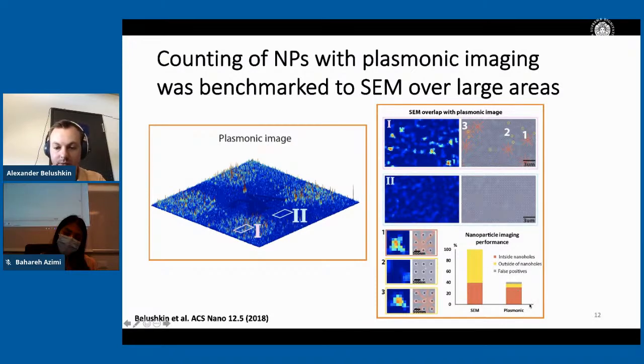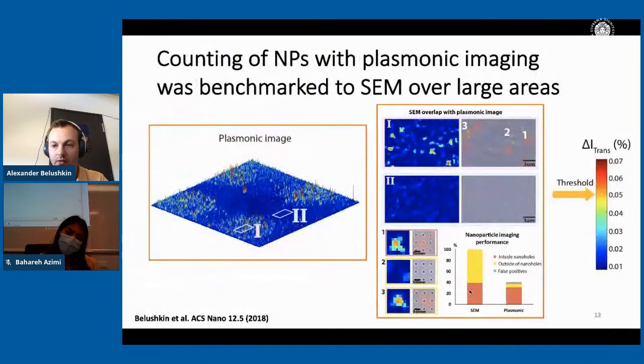And these are, in fact, those we can see on the plasmonic image as well. At the same time, we can see some of the particles that are outside the nanohole but close to the rim. This is due to the plasmonic interactions, which you can find more details about in the paper if you're really interested in the plasmonic nature of those effects. But overall, we can see about half of the nanoparticles that are either inside the holes or close to the rim.